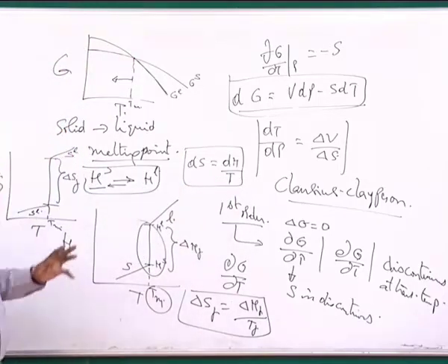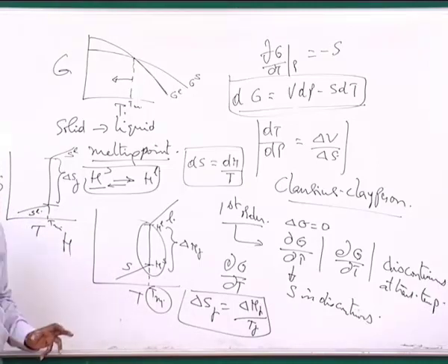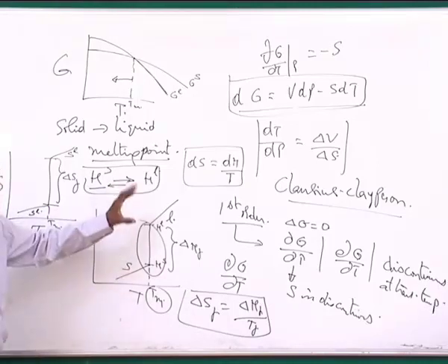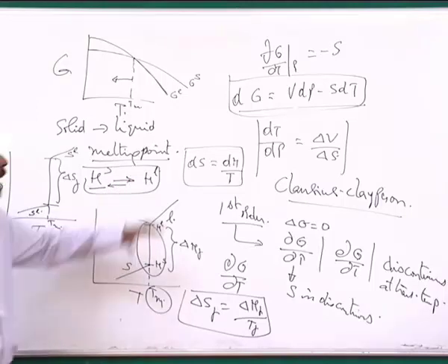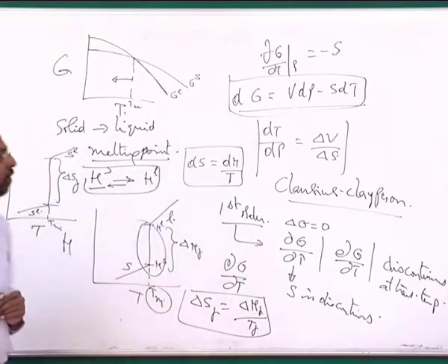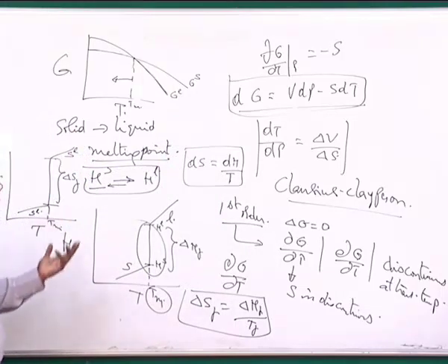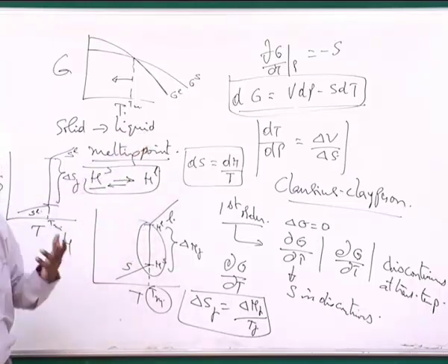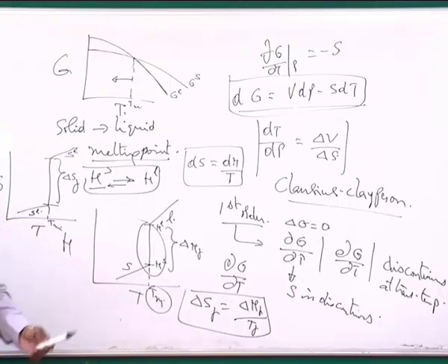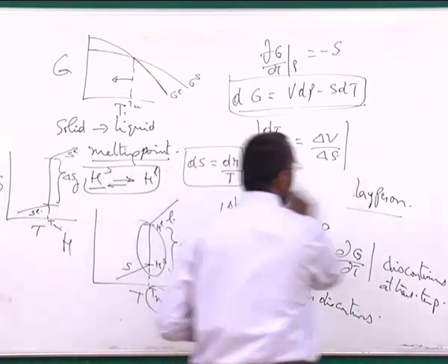So first order transformations are all those where suddenly you see a change in the enthalpy at the transformation temperature, and we can happily use this property change in order to identify at what temperature this phase is transforming to another, and also what is the enthalpy associated with it, by simply using techniques such as calorimetry, and that is what we call thermal analysis.